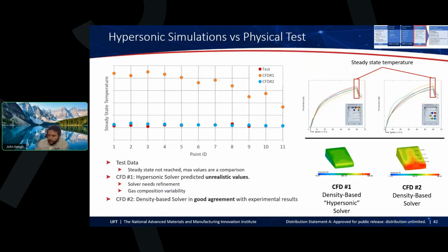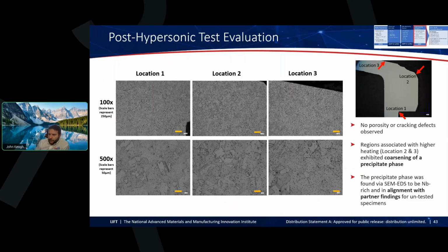You want to look at ablation, right? Any sort of microstructural changes based on heating, cracking, etc. We didn't observe any porosity or cracking. There were some regions with higher heating, so say locations 2 and 3. We did observe some coarsening of the precipitate phase, and found that really by EDS. That was a niobium-rich phase. And it was, of course, in alignment with our other partners' findings as well for some untested specimens too.